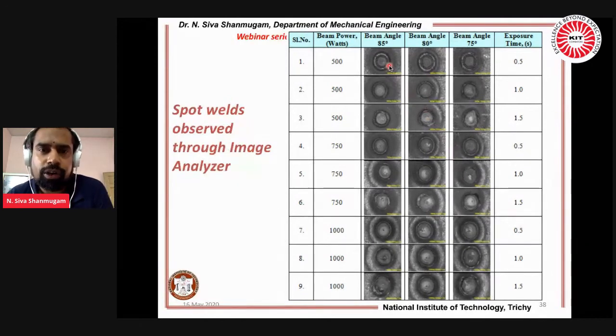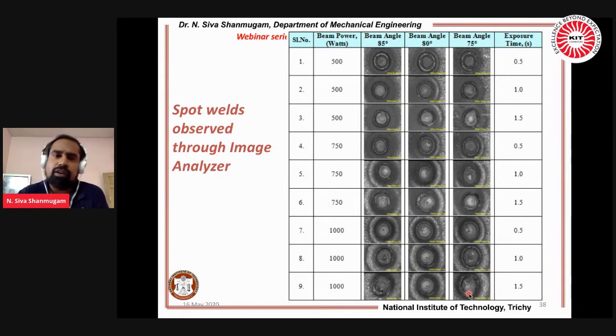I already told you, if it is a straight beam, you are getting almost a circle, but we are operating at around an 85-degree beam angle. You are not getting a circle, you are getting only an elliptical profile. For a wider beam angle, it is almost elliptical. For a very high exposure time and a very high beam power of 1000 watts and a beam angle of 75 degrees, you are getting a very elongated elliptical shape on the top surface.